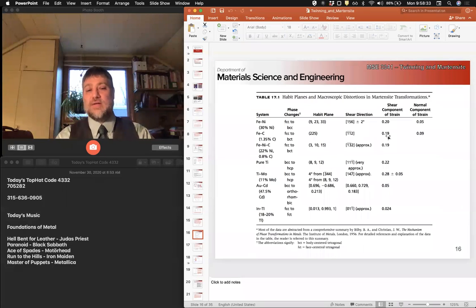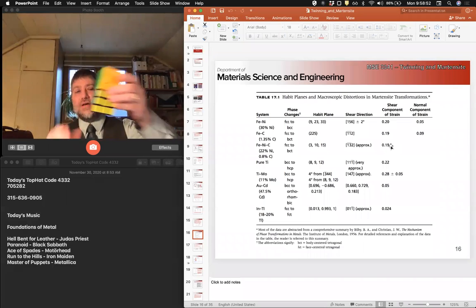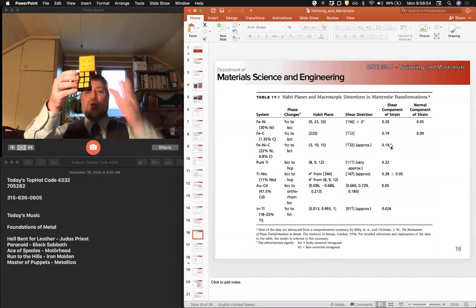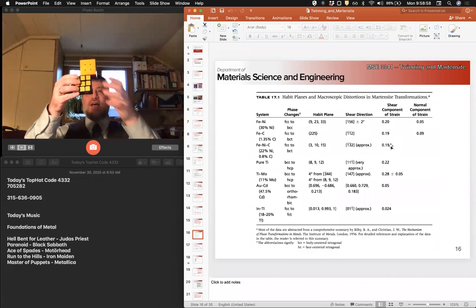0.2%, right? So 2 orders of magnitude higher. So this should tell you something about this transformation. This Martensitic transformation is exceptionally violent. What happens if I have a 20% shear? What happens in these neighboring grains? How does this get accommodated in a polycrystal?